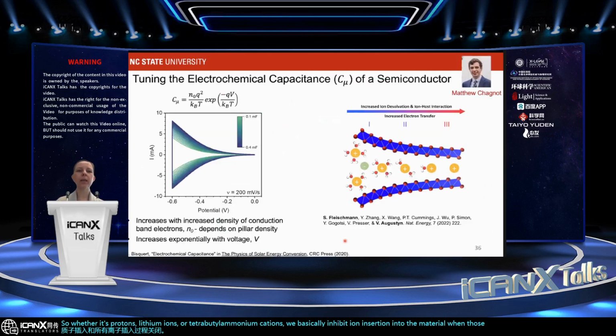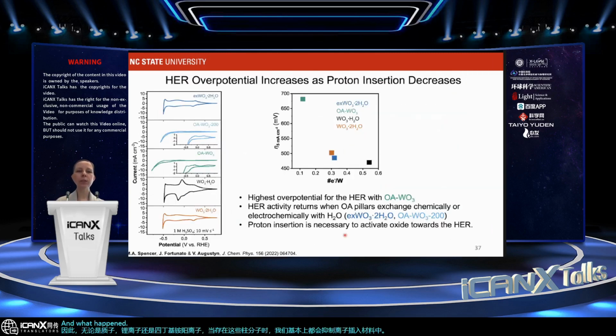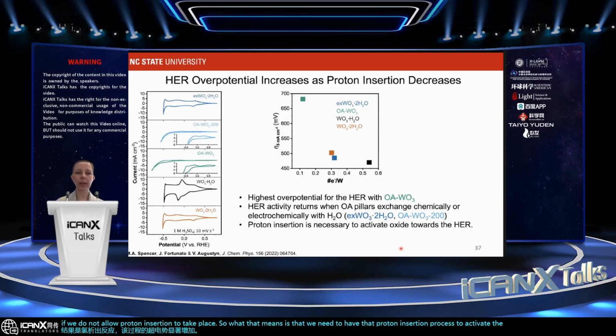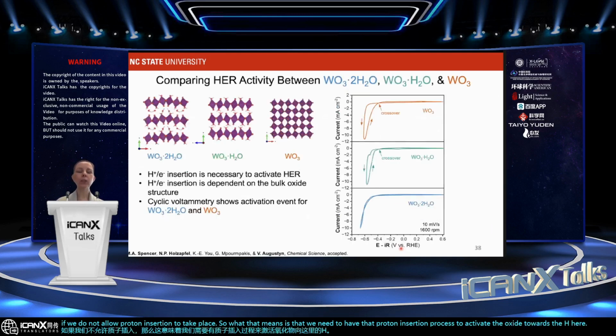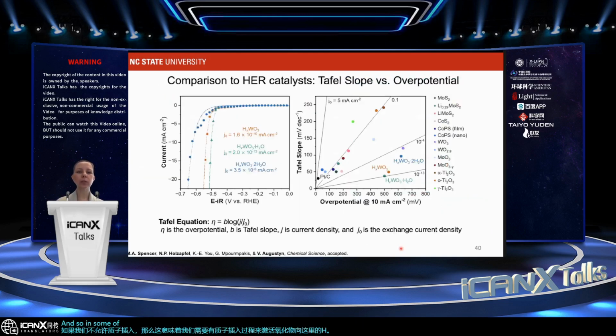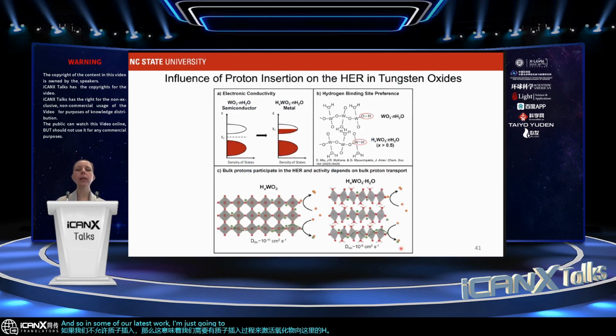And what happens as a result is that the hydrogen evolution reaction, the overpotential for that process is significantly increased if we do not allow proton insertion to take place. So what that means is that we need to have that proton insertion process to activate the oxide towards the HER. And so in some of our latest work, I'm just going to go through this quickly, we've further analyzed